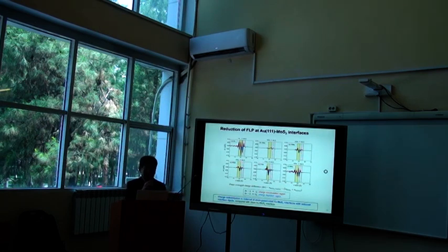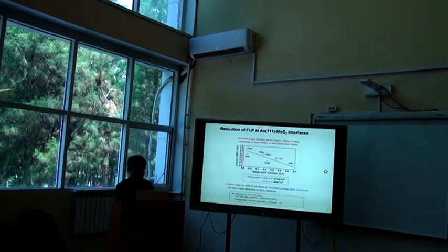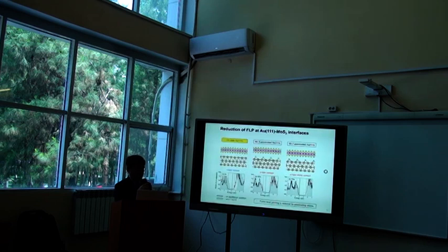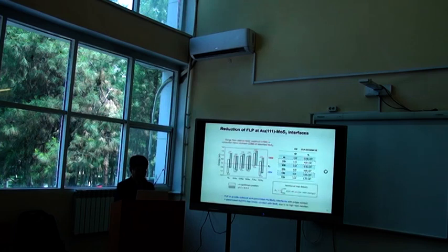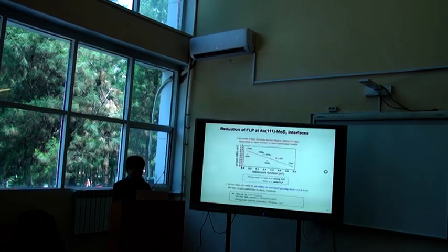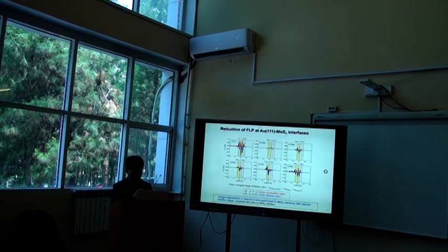So now you can see that to know how much Fermi level pinning occurs, you need to calculate the density of states, the range from VBM to CBM, the pinning factor, and finally the charge density distribution too. After combining all the results, I can conclude that using atomic species at interfaces makes the Fermi level pinning much reduced.